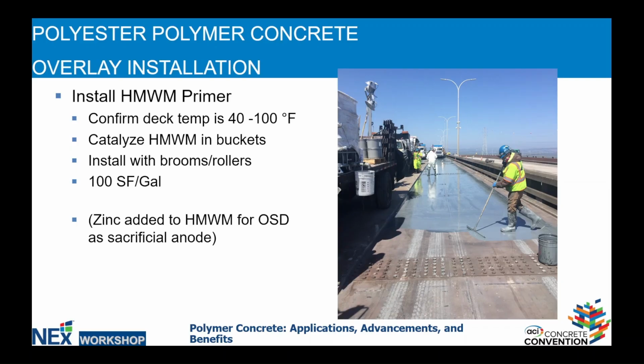The installers, as you see here, they're spreading with squeegees. They've already poured the material. This is the primer that is being poured out from buckets after mixing. It could be spread with squeegees, could be spread with brooms. We also ask the installers to mop out and make sure that the primer does not build up or puddle in certain areas where that could be a little bit of a weak spot. You always like to try to remove the thicker primer. Thin is better in a case like that.